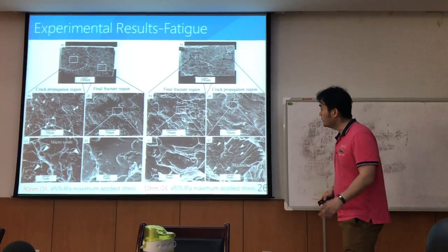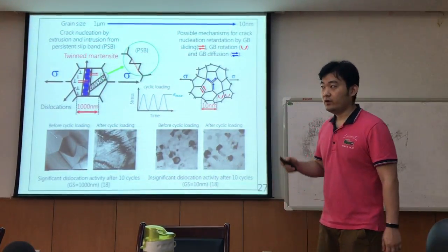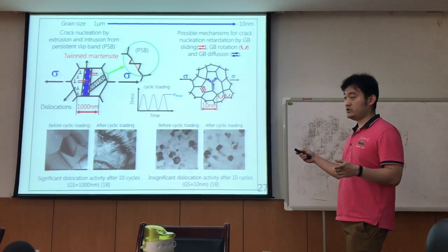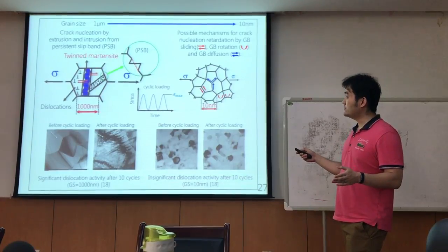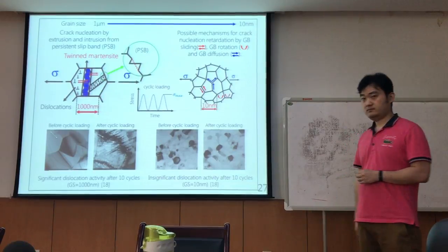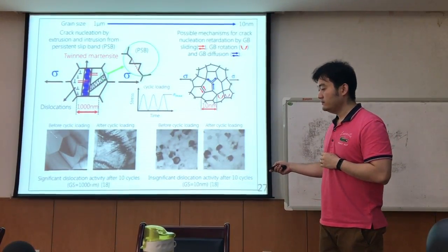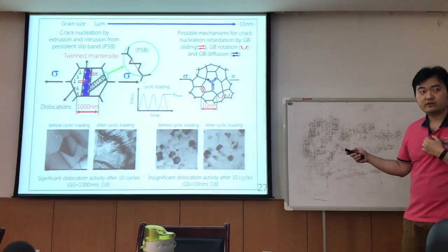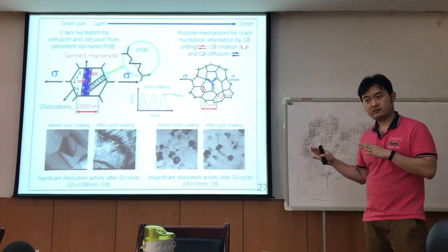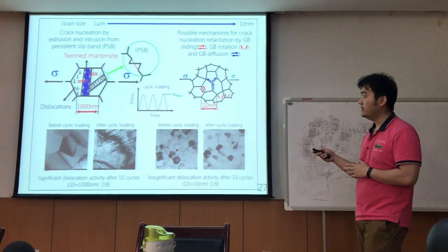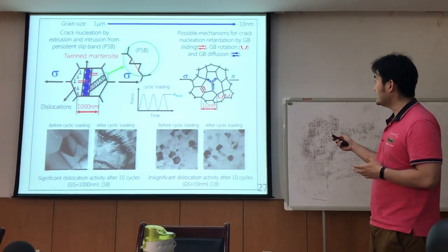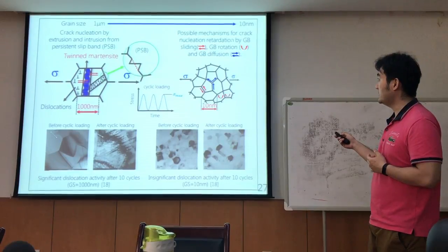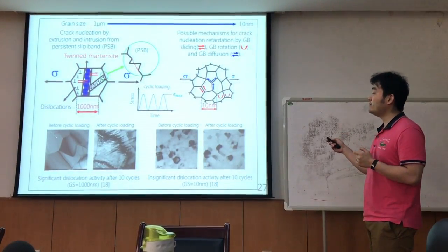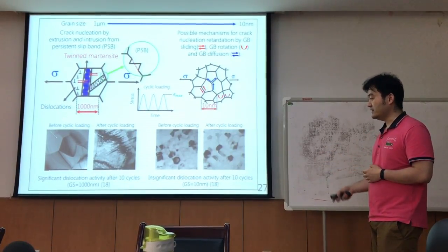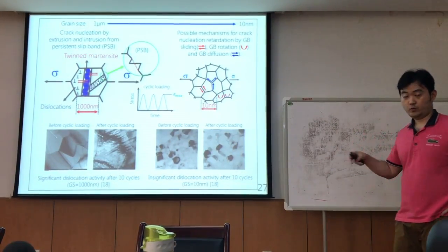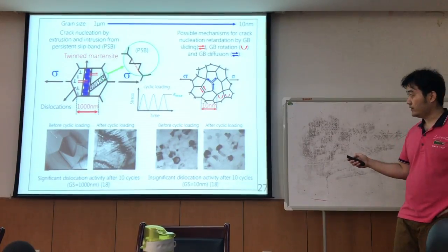So we're thinking, when the grain size decreases, for large grain, the fatigue may be caused by the crack nucleation, or the extrusion and the intrusion from PSB or twin martensite. Okay, this was observed by others. But for small grain nickel titanium, since the phase transformation or slip bands were banned, we think there are some possible new mechanisms for crack nucleation retardation, like grain boundary sliding, rotation, or grain boundary diffusion happening for small grain nickel titanium SMA. But these are our thinking. We need some evidence to prove we are correct.